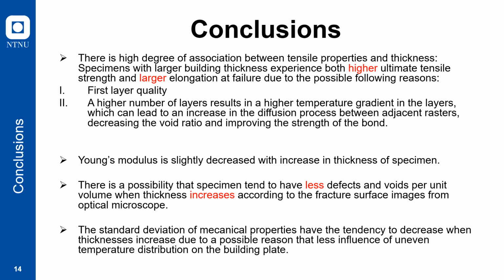And the standard deviation for the mechanical properties has a tendency to decrease when the thickness increases. So there's less discrepancy in the data, possibly because uneven temperature distribution on the building plate will have less influence. For the specimen fabrication, we have 5 specimens for each case, and we fabricated 5 of them on the same plate, so there might be some uneven temperature distribution on the plate, which may cause discrepancy in the data. And when the thickness increases, the influence of that gets smaller.